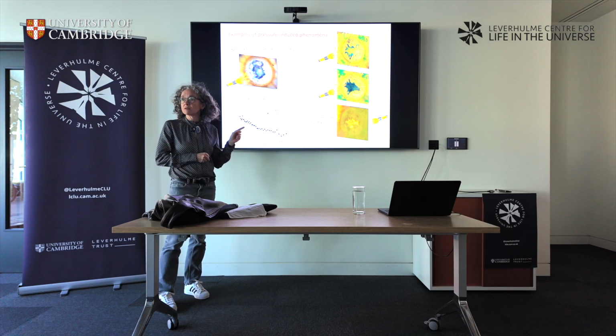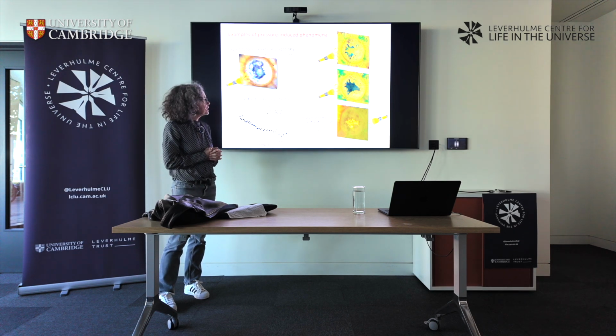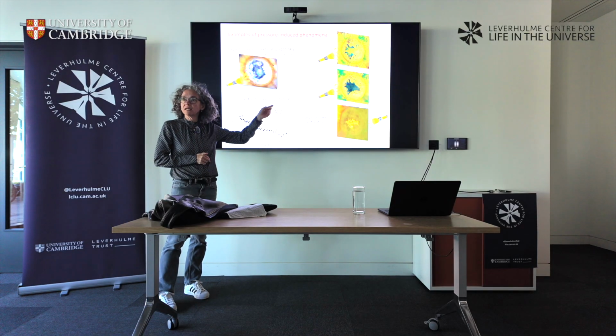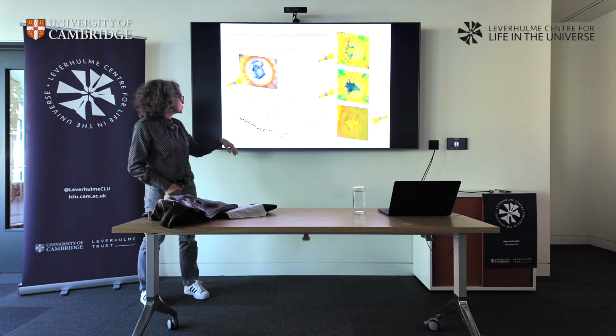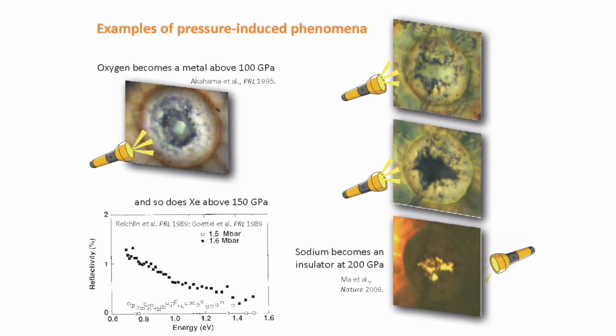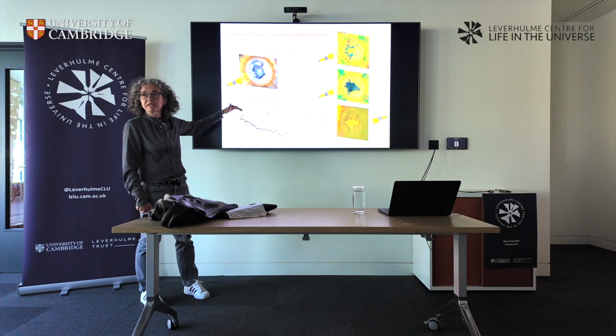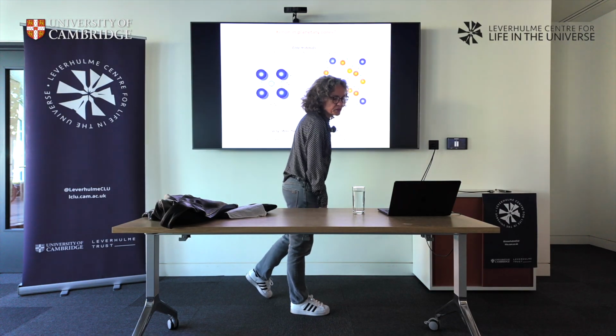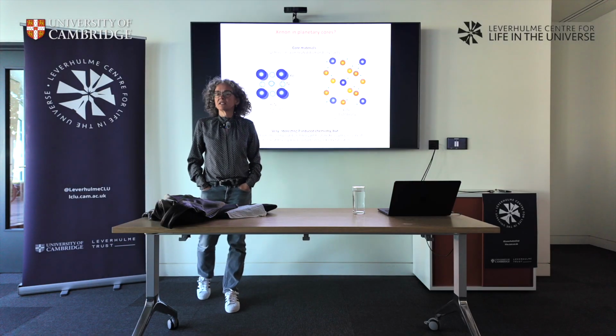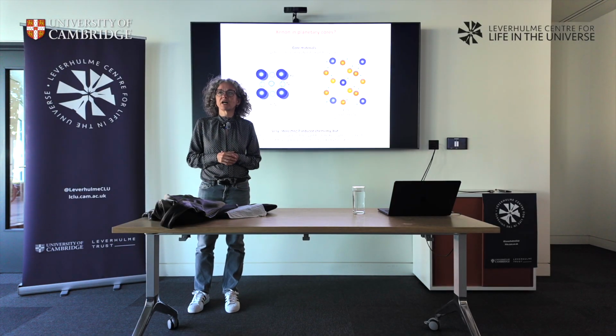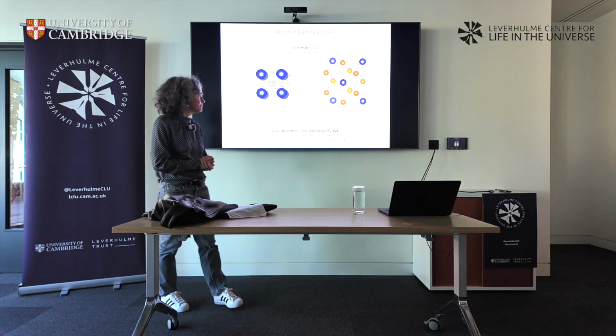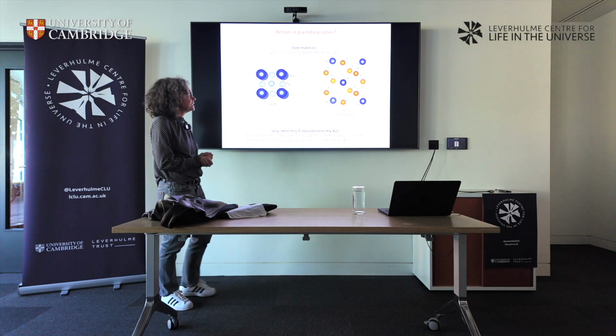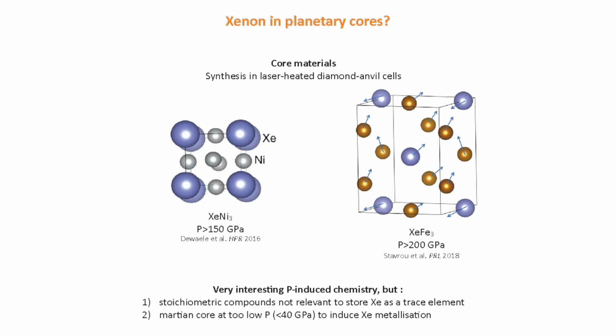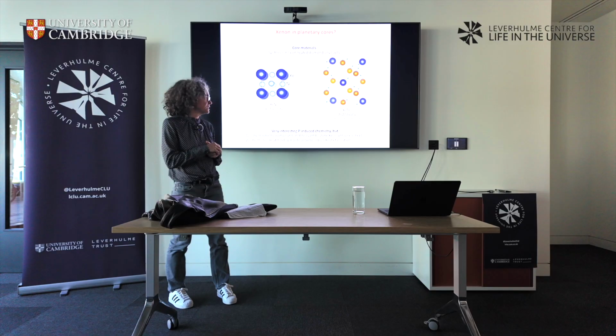Xenon also becomes a metal, as a matter of fact. At pressures that we encounter in the Earth core, 150 GPa, it's just the top of the Earth core, it becomes a metal. Here it was reflectivity measurements, and you see that above 150 GPa, reflectivity goes up. It reflects light, so it becomes a metal. Because this was observed, one of the initial thoughts was, well, xenon is in the core, because the core is made of iron. If xenon becomes metallic, it can make an alloy with iron. And as a matter of fact, people have synthesized xenon-nickel and xenon-iron compounds at core pressures, very high pressures. So it's a very interesting chemistry.